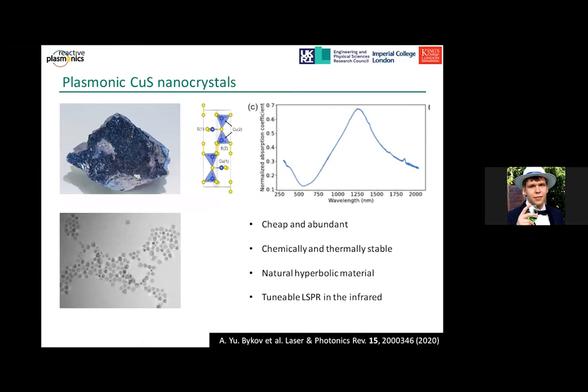is copper sulfide. In the wild, copper sulfide is a heavily doped semiconductor, which you can find as this blue naturally occurring mineral. In the lab, however, you can manufacture it in the form of nanoparticles like here, which produce a strong, very good quality localized surface plasmon resonance in the infrared close to telecom wavelengths, which, in addition to being cheap, abundant, and chemically stable, makes it a very desirable alternative material.